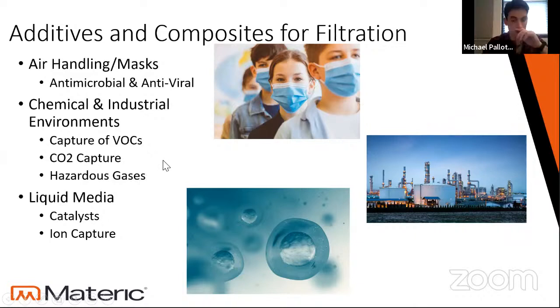And as Steve was mentioning, sometimes your nanofiber is your filtration media, and sometimes it doubles as a carrier for those additives. So in the second case, like chemical and industrial environmental filtration, the nanofiber acts as both a filter and a carrier for those additives, which can be used for either chemi-absorbing or doing some reaction to the volatiles that are coming off that need to be filtered. And in some cases, between the second and third bullet, the chemical and industrial and the liquid media, you'll find that you could tune your nanofibers and their area density to help filter different types of materials, whether it's a liquid or a gas.